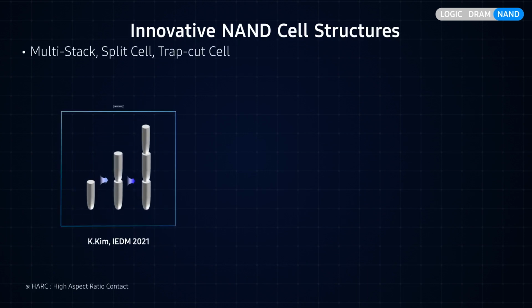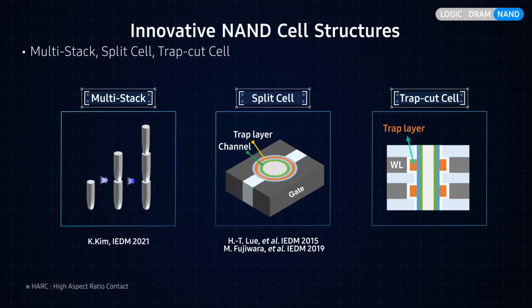First, let's have a look from a structural point of view. As we stack more and more layers, high aspect ratio contact etching to form channel hole becomes extremely challenging because a vertical pitch of the single layer is no longer scalable. Therefore, we need innovative cell structure.